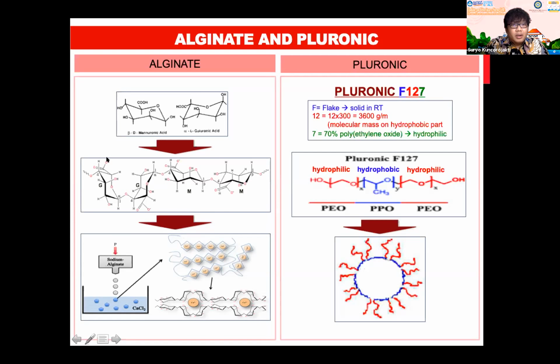Based on the study, many researchers mentioned that the G blocks play an important role in gelling formation. When the alginate is extruded into the gelling solution, such as calcium chloride solution, the gelling formation will occur. The conformation of the alginate looks like an egg box structure with the calcium ion in the center, making an interlock in the G block. So that's why they can polymerize.